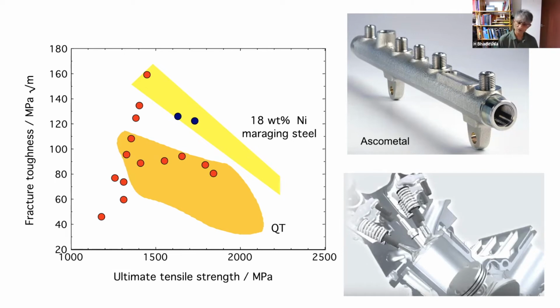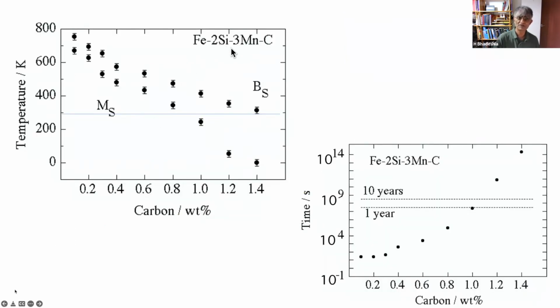So I said to you that we can control the scale of the structure by controlling the transformation temperature. So the question arises, what is the lowest temperature at which you could produce bainite? Well, we have the theory. So we did some calculations for this system and varied the carbon concentration. And as long as the martensite start temperature keeps away from the bainite, you're okay. And what this theory shows, and this is room temperature, is that in principle you could produce this at room temperature. But the kinetics of transformation would take about 100 years. So you could treat the steel like fine wine and keep it for 100 years and then sell it. But I have yet to find a producer who will agree to invest in that way.